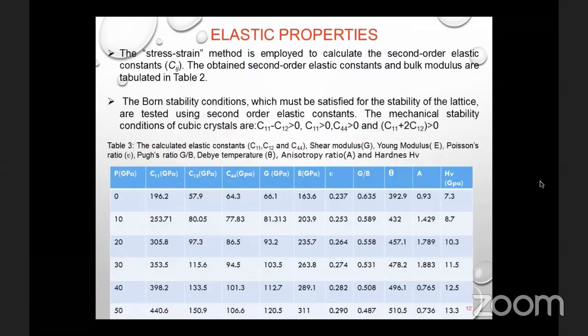Elastic constant is defined by the reaction of solid under external forces. By using calculated elastic properties like shear, bulk, Young moduli, and Poisson ratio, the stability of the material can be determined. To calculate elastic constant, we use the strain method. Obtained results are given in table 3. For mechanical stability, elastic constants should satisfy the stability conditions. According to the obtained result, elastic constants of this material are stable, mechanically stable even under pressure.